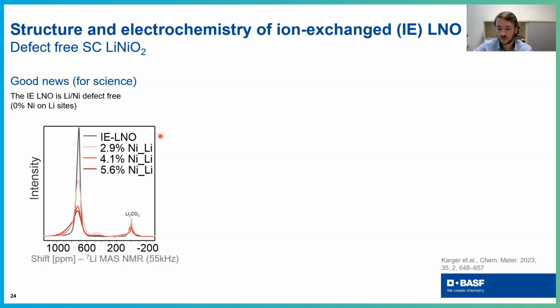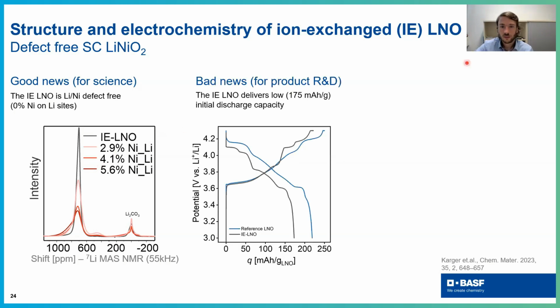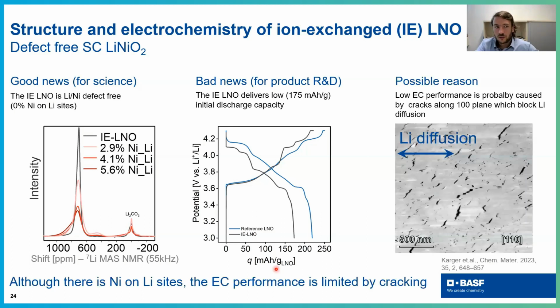Now, rather bad news for, let's say, product development is that this material, although it has no nickel lithium exchange, performs very badly in the cell. So if you compare it to the conventional LNO material, our ion exchange sample has low discharge capacity, and it delivers only around 175 milliamperes per gram of discharge capacity. So why is that? Well, the answer is actually here.